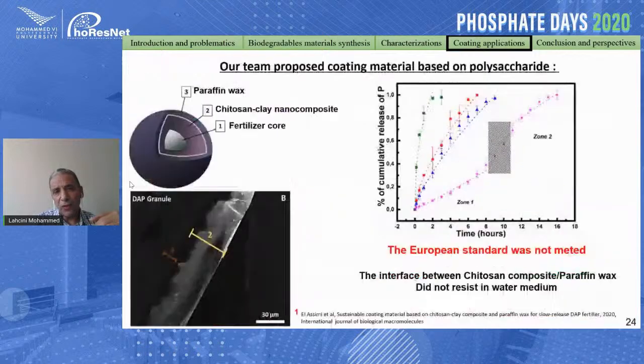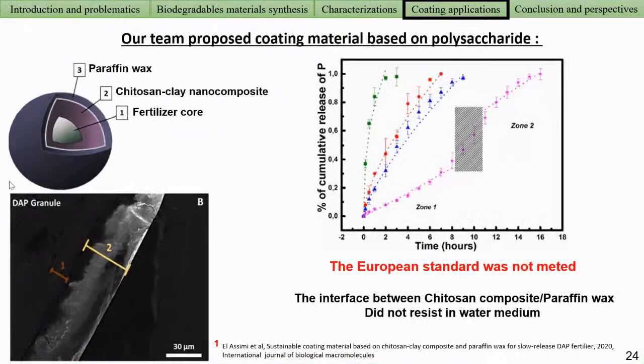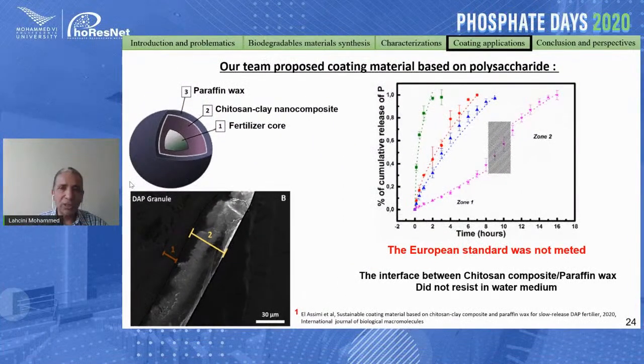In our group, we first tested the polysaccharide chitosan as a coating material, because it is the second most abundant polymer and easy to prepare. We used it as the inner coating, and we also used wax as the outer coating. This is because chitosan is really hydrophilic, it absorbs water, and we cannot slow the release only by coating with this composite. For that reason, we use paraffin wax as the outer coating, but even with double coating, we have total release of nutrient after 16 hours. It's not enough to say that our coating agent is for slow release.